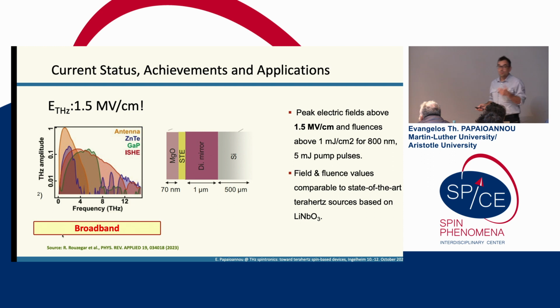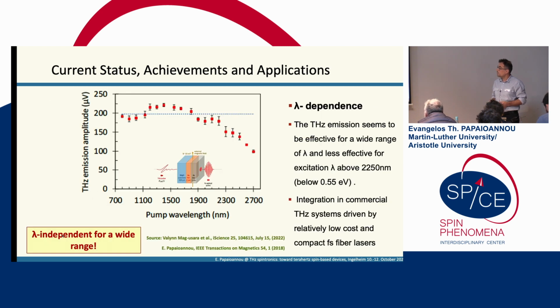Sorry. So we are aiming for really strong signals, but another good property of the terahertz emitters is that they are more or less independent of the wavelength that we use to excite them. So we have seen this in different wavelengths, and in a recent publication we tried to go even further in the wavelength, and you see more or less there is a kind of plateau where the terahertz emitter works quite nicely and then starts to degrade after 2000 nanometers. And this is very good also for applications, since we are here to discuss also possible applications. These emitters can be integrated in commercial femtosecond fiber laser systems.